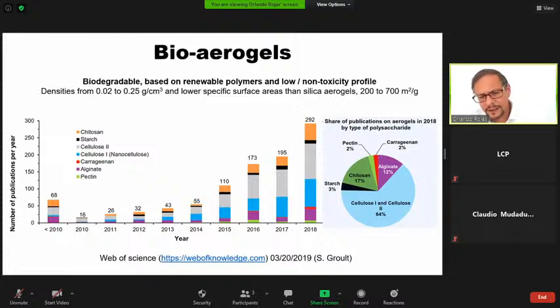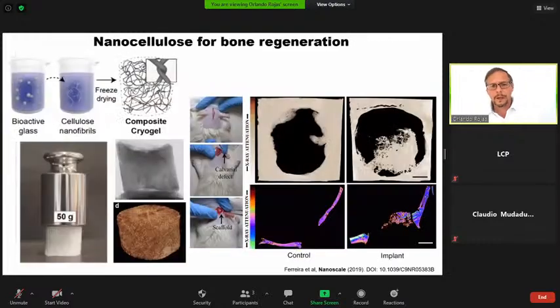My point here, at least in our work and those that are around, is the idea of using cellulose and including nanocellulose to produce aerogels. And if you see the development in the area, you can see that the growth is actually increasing exponentially or at least consistently. And in many of the cases, we see cellulose as one of the components for these aerogels. So one of those actually comes from work from Campinas, and this is a visitor in the group, Felipe Ferreira, that did some work in this area. And the main message here is that combining nanocellulose with bioactive glass was a very interesting cryogel that was produced by freeze drying that allowed the regeneration of bone.